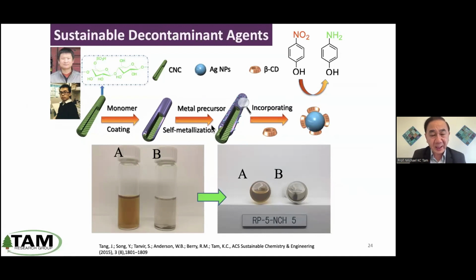As you can see, A is our dispersion. You can see very good dispersion over a long time. B is the silver nanoparticle prepared without this coating. As you can see at the bottom, you have agglomerates of this silver in the solution.